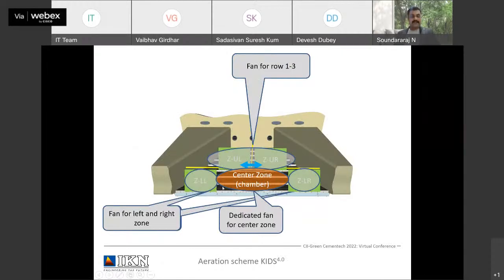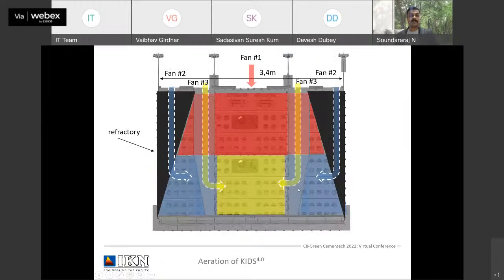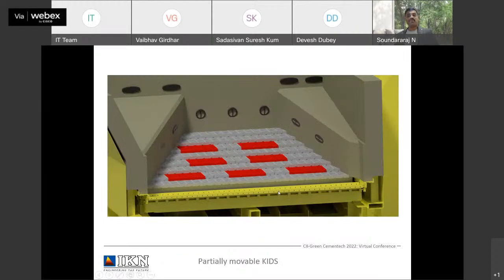The center aeration in this KIDS 4.0 allows us to create a valley instead of a hill in the center. In case of coating, when too much coating collapses, normally it will try to stay at the center of the cooler and it will divert the fines towards both sides and create a red river. With the help of this dedicated fan aerating in the center, we will be able to push this coating material to the corner so that the bed will become even. So the counteracting of these challenging operating conditions can be done with the help of this chamber aeration and the center aeration. And now, how to counteract the snowman?